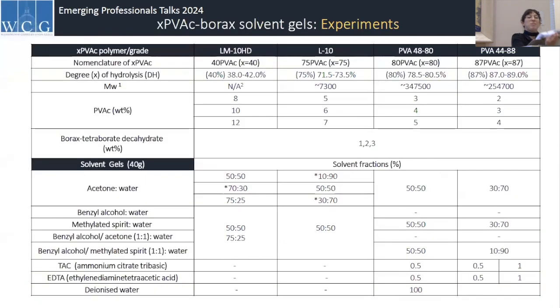Next slide, please. So this is basically a snapshot of all of the experiments that I've run. I've been running more, but this is more cogent. What I was looking at was 4 different polymers, so 4 different hydrolyses, low hydrolyzed polymers and high hydrolyzed polymers, and looking at incorporating a range of different solvents that are applicable for cleaning gilding. And you can see them down the side there. Varying solvent ratios, and all of these gels have a proportion of water in them as well, because that's necessary for the borax salt as a crosslinker, and it also does assist in the formation of the gel and the cleaning efficacy.